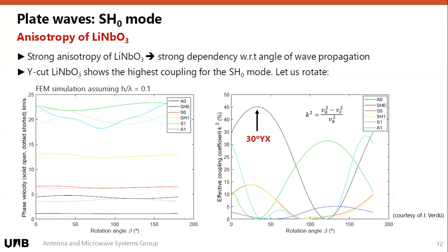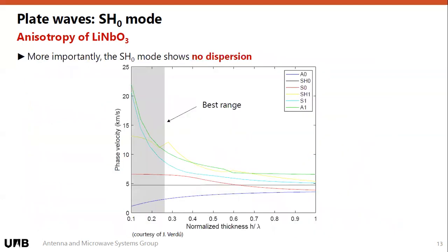Okay, now we know the cut we're going to play with, because you get the maximum coupling from here. There's another thing to revisit. Interestingly, and more importantly, the SH0 mode shows no dispersion with the plate thickness. So you can sweep here the thickness of the plate with respect to lambda, and what you can see is that your phase velocity is not changing. This is a really important aspect because it allows you to choose the region in terms of the h over lambda ratio that you're going to be working with.